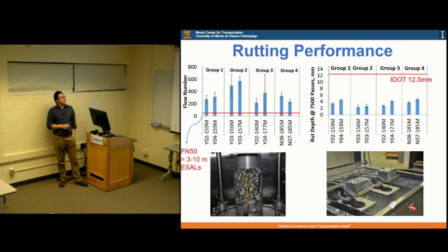And also if you're using the Hamburg wheel tracking, the threshold is 12.5. So all the rut depths are far below that threshold line. So we are seeing that all the mixes have very good rutting resistance, which means that if you put a lot of RAP and RAS in your surface mixes, you end up with very high rutting resistance.